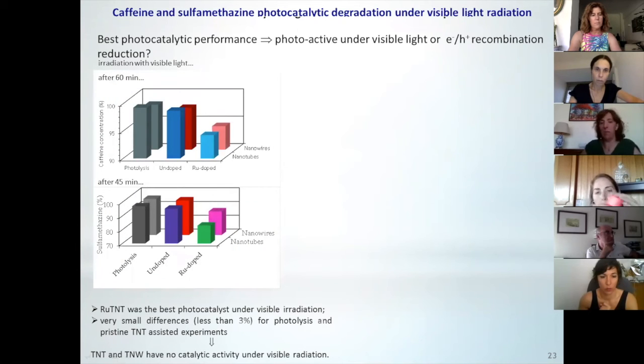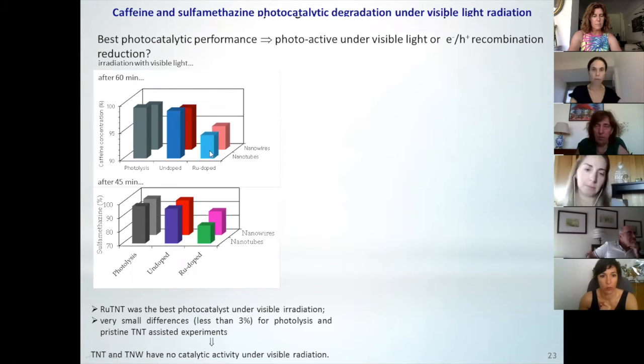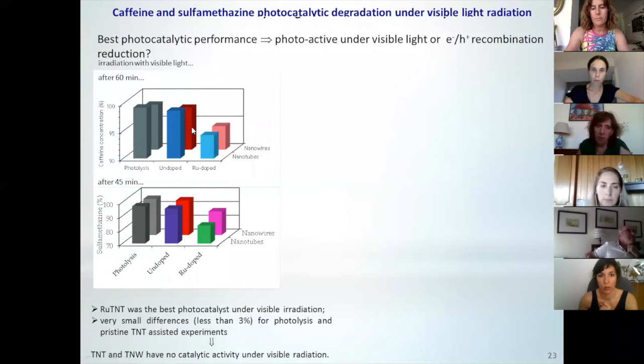So, they are catalytic. So we would like to know why they are catalytic. Is it because they absorb in the visible, or are we playing only with the reduction of the recombination? So let's try to see what happens when we use the visible radiation. The conclusion is the same for caffeine and for sulfamethazine. And as you can see here, of course, the whole process is slower because we have less energy, but it's obvious that when we have the doped samples, we have an improvement in the photocatalytic performance of this material. So they are active under visible light irradiation.